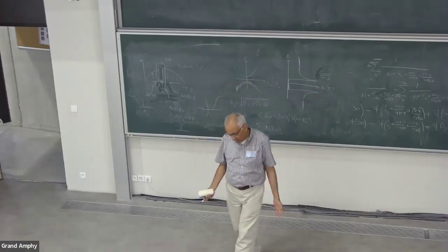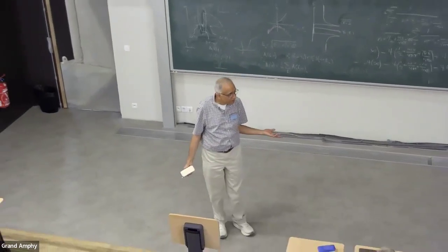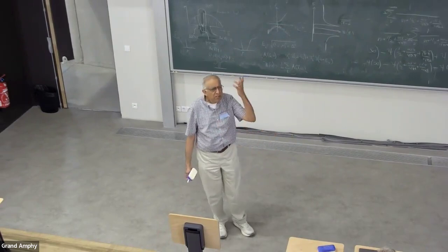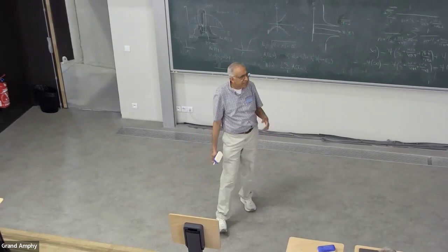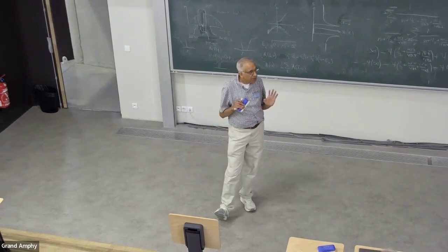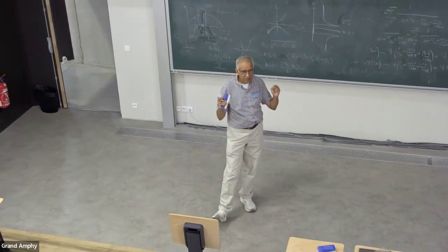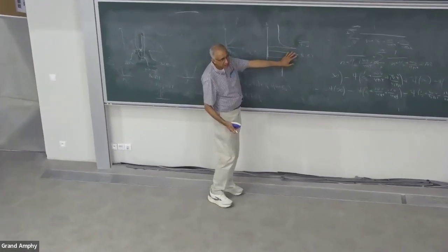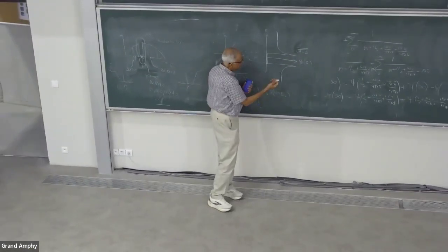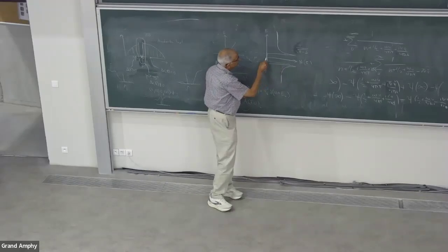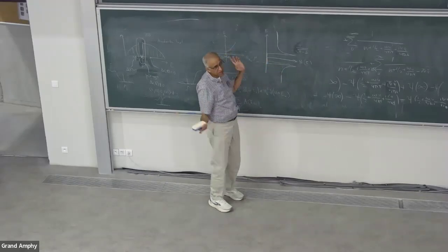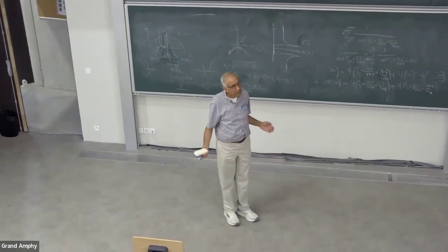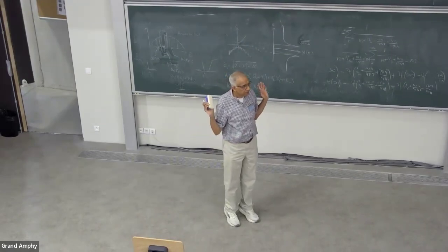So tunneling people put in what they call the Dynes parameter. Every time they have an E, they will say E plus i gamma. Where does the gamma come from? It came from something, disorder, inelastic scattering, something which we don't have too much knowledge of, but which is broadening my spectral function. As soon as you broaden the spectral function, all this shape changes dramatically. Even at zero temperature, very low temperatures, it will give you something like this, and if you make it very broad, then it will look really different. In some cases, we understand where this comes from in detail. In most cases, we don't.